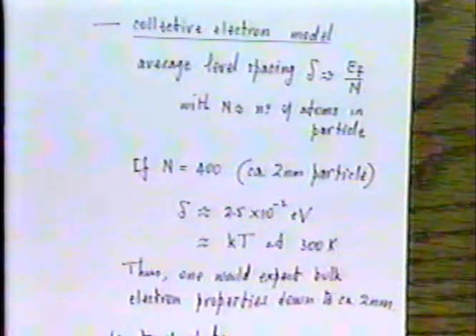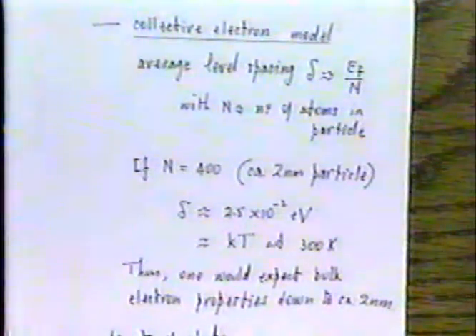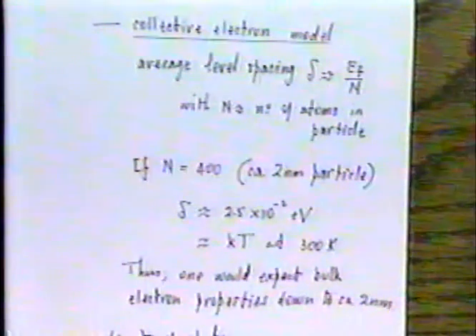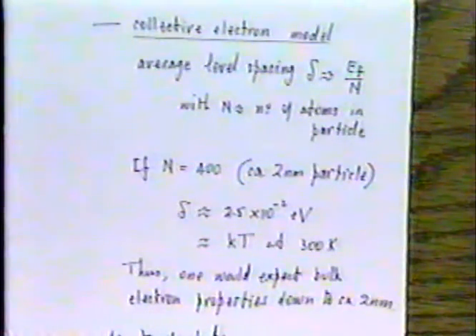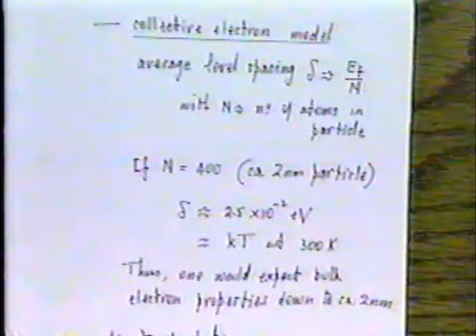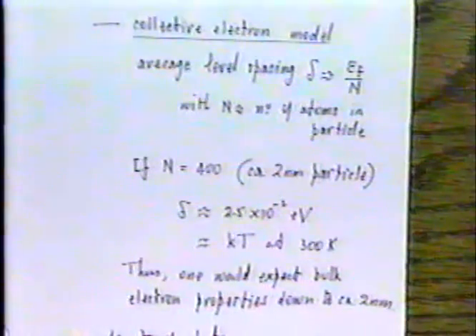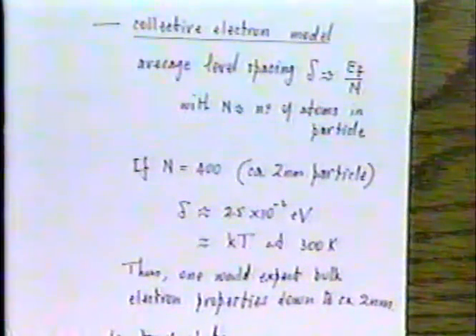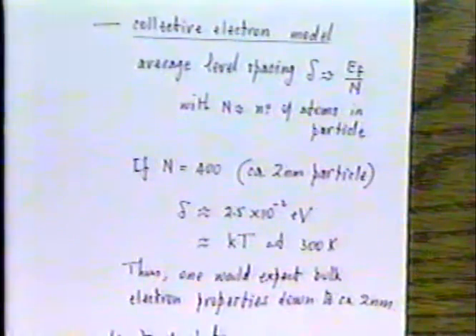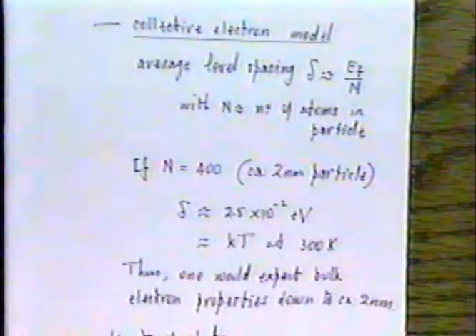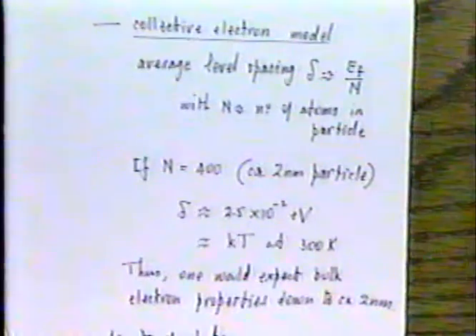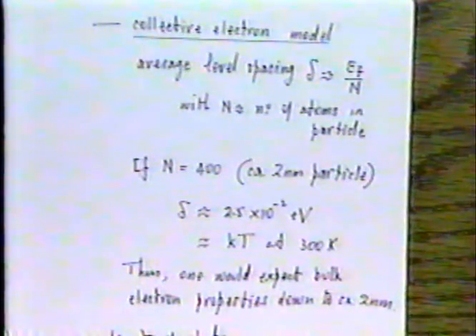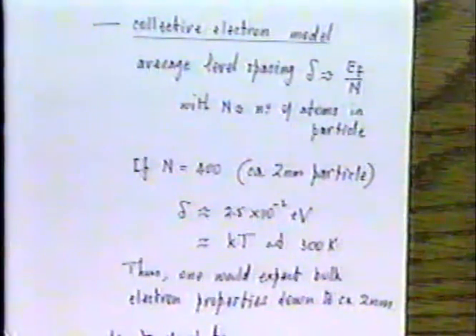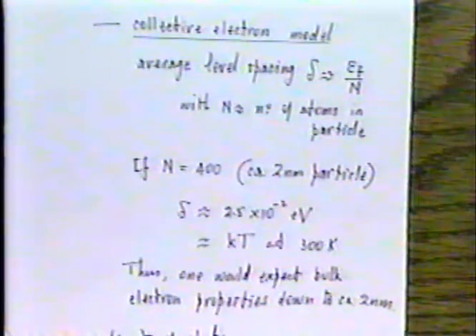will probably have electronic properties that are significantly different from those of the bulk metal. And in fact, it goes in the direction, as you might expect from the argument that I presented to you at the beginning of this little discussion, by comparing single atoms with crystals. It goes in the direction that as the particles get smaller, below 20 angstroms, the energy of electron removal increases. That is to say, if you want to use an electron for a chemical process at the surface of the particle, then you've got to pay a higher price in energy to get hold of the electron as the particle size goes below 20 angstroms or thereabouts.